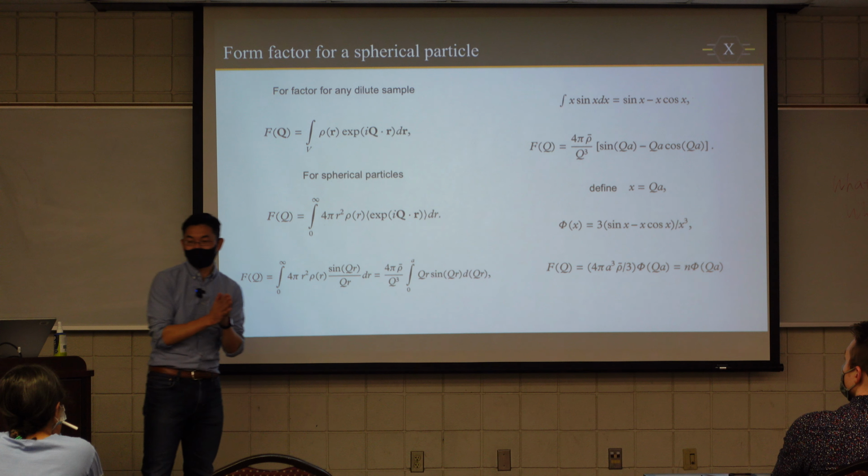So a very interesting part is the first dip. This 0 is translated to this 0. I think this textbook artificially showed a gap. There should not be much gap, unless this is not plotted exactly to 0. If there are some backgrounds, then that's reasonable, you have a little bit of gap. So the first minima in your measured intensity has a significant physical meaning.